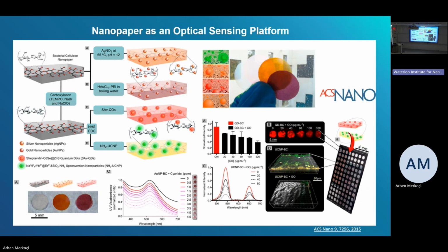So the nice thing here, as I said before, as in the case of pH paper, is that if you immerse this paper, you put this in contact with something that you want to detect. For example, we did some simple experiments with cyanide, and given the fact that cyanide can corrode the nanoparticles, for example the gold nanoparticles, we see the changes of the plasmonics, and we correlate this plasmonic change with the concentration of the cyanide. Of course, this cannot be selective yet, because if you have some compounds that can interact and change the nanoparticles, you do not know what is the cause of these changes.